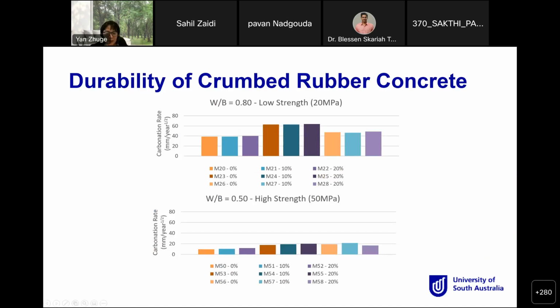We can see the lower strength mixes M21 and M22, with 100% Portland cement, show almost no difference in the carbonation test compared to the control group of M20. So that is your M20, that is M21, and that is M22. These are very consistent. And even when you have fly ash, the carbonation rate increased a bit, but the results with and without crumb rubber are still very consistent for carbonation. And the same thing for using slag, the results are pretty consistent. And the same thing applied for the higher strength concrete. So really, there's no difference in the carbonation effect for the crumb rubber concrete.